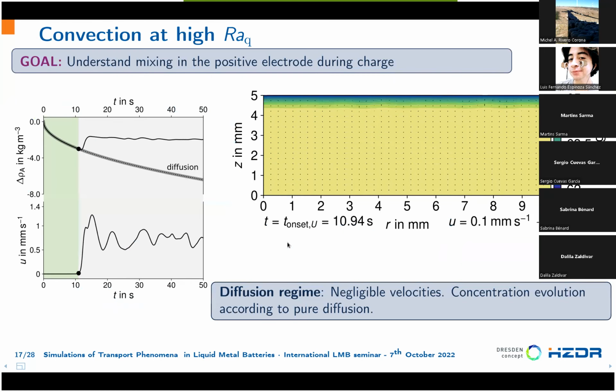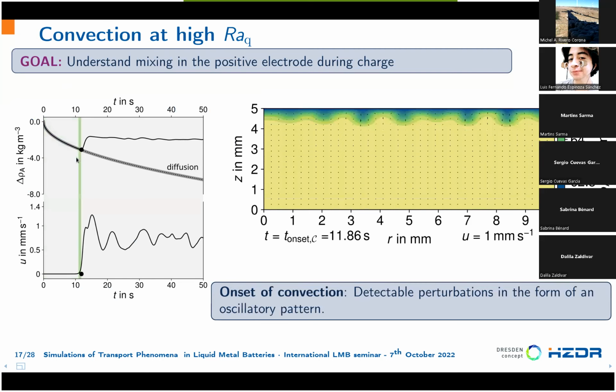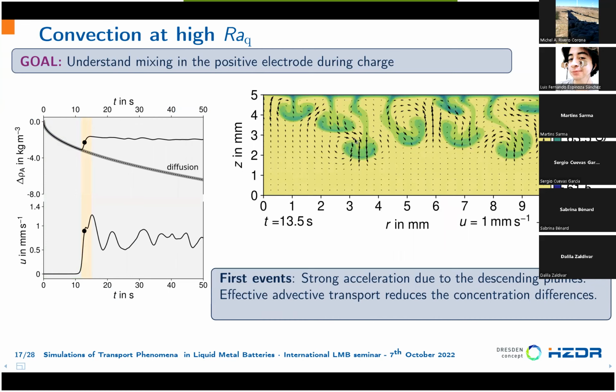So, solutal convection in 2D domains. Here is the reference case that I discussed before. It starts with diffusion. So we have negligible velocity and the concentration evolves as pure diffusion. And here we see very parallel lines in the concentration field. Then we have the onset of convection and we see this wavy pattern that reminds of Rayleigh-Taylor instabilities. And this detectable perturbation then leads to the first events, which are these plumes that are going through the domain.